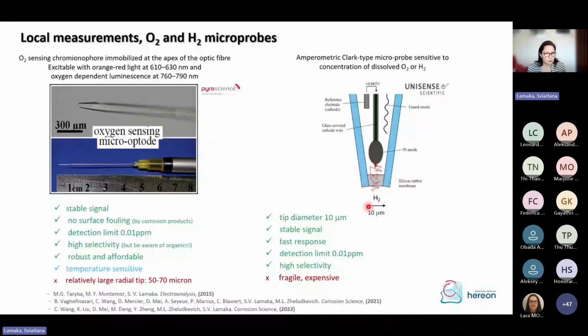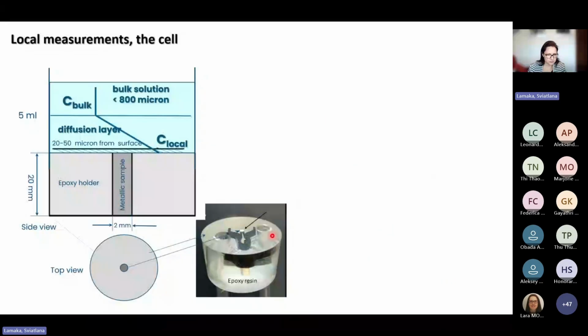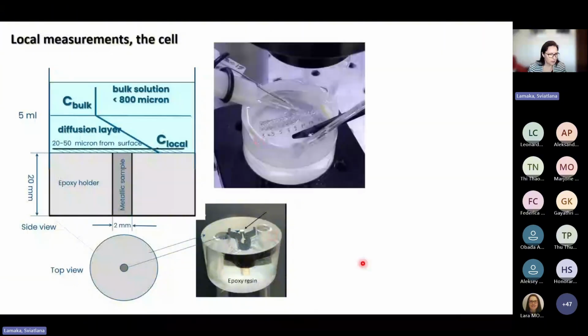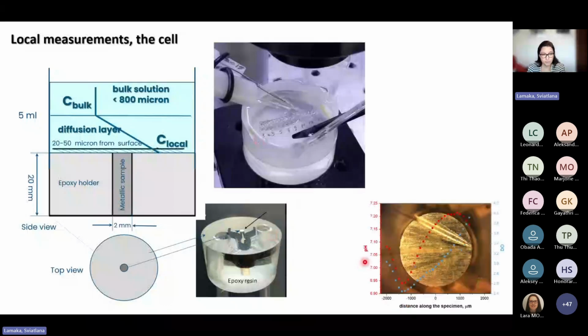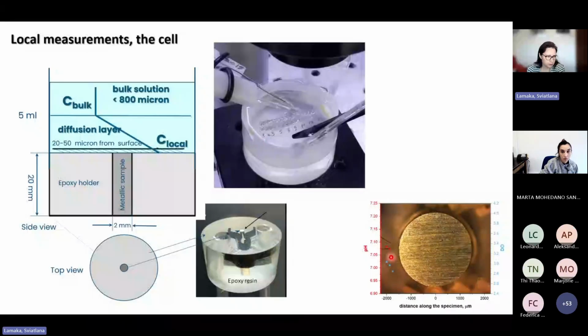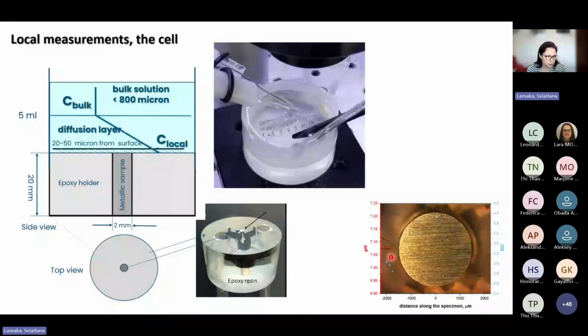So this work was a collaboration, and colleagues from AkzoNobel measured leaching of lithium from the coating. Then colleagues from TU Delft quantified corrosion inhibition effect. And the finite element model of this system was built by colleagues from VUB. And our task here was to validate model predictions with SVET measurements and also concentration of dissolved oxygen and pH in this case. So we worked with coated samples, either reference without lithium carbonate or the one containing lithium carbonate, and then the scribe of 1 millimeter, 100 micrometers deep. Very reproducibly, these scribes were produced by Airbus.